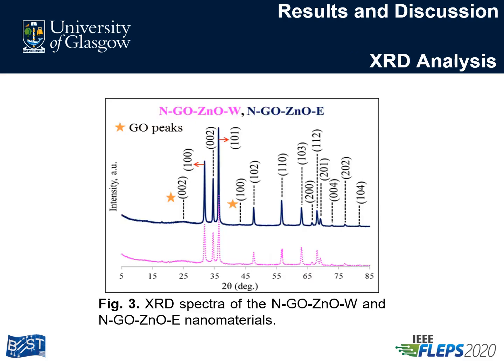Next, the crystallinity of both nanomaterials was evaluated from the XRD spectra. As can be seen in the figure, both nanomaterials showed several broad peaks signifying the small size of the zinc oxide nanoparticles. The pronounced diffraction reflections showed an agreement with the wurtzite hexagonal crystal system of zinc oxide. The enhanced diffraction peaks of 100, 002, 101 and 103 crystal faces indicate a polycrystalline behavior, accompanied with preferential zinc oxide crystal orientation along the C-axis, which provides hexagonal rod-like morphology.